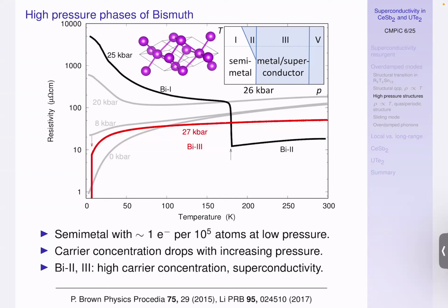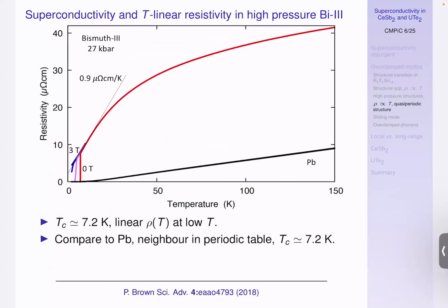And in the Bismuth-III phase, you have superconductivity at about 7 Kelvin. You have a high carrier concentration. And what was striking, you also have this very steep linear temperature dependence of the resistivity, like we just saw in this material with the structural phase transition.